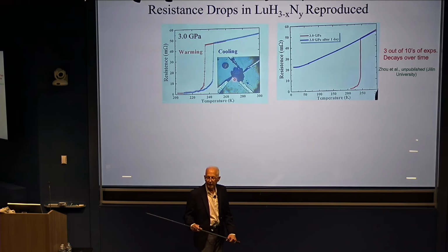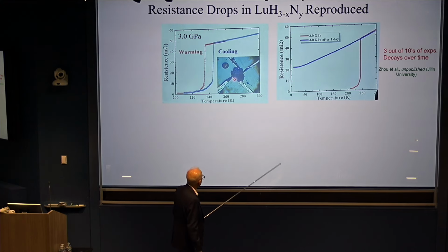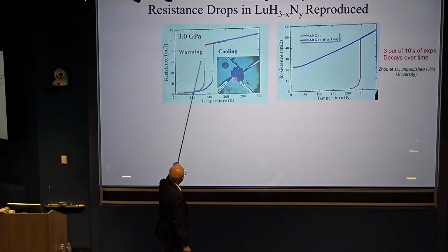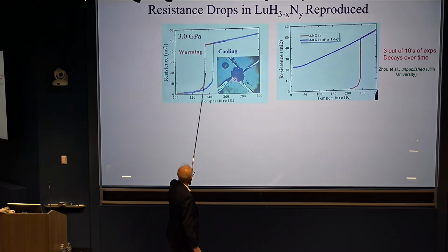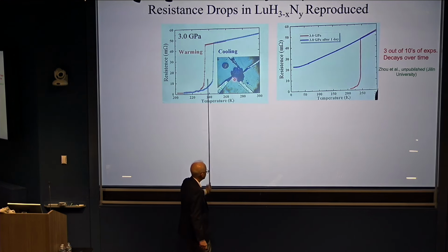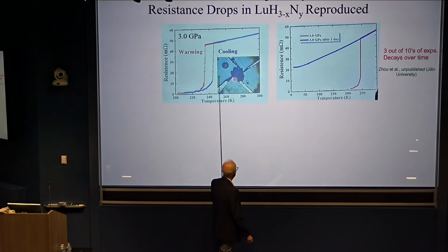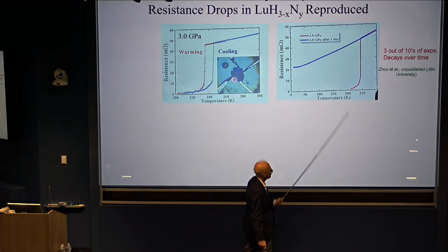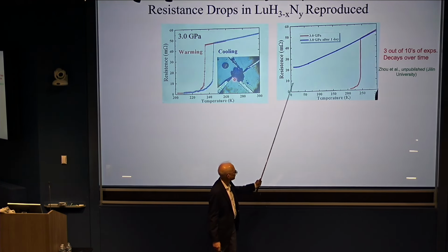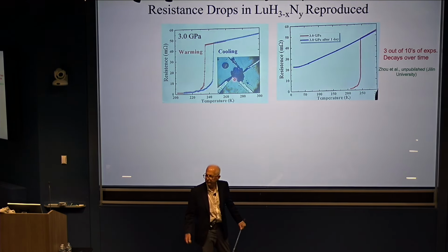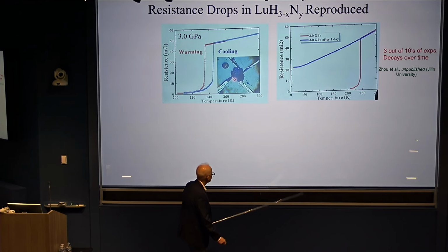And what I've learned in the last 6 months or so, in fact, a group in China has seen something quite similar. Here's a similar kind of sample, and they see a resistance change at about 240 Kelvin, really quite close to what we found. But there is this time dependence. After several cyclings, this goes away. So something intriguing is happening, but we don't fully understand.